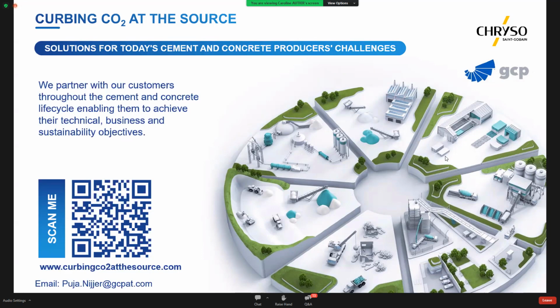Yes, sure. Calcined clay generally requires activation on the early strength, but they also have a particularity to have high water demand. So it's a characteristic we need to consider when we customize products for a customer. So it depends on the quality of the clay, of impurities, fineness, and so on, and also the overall cement composition.